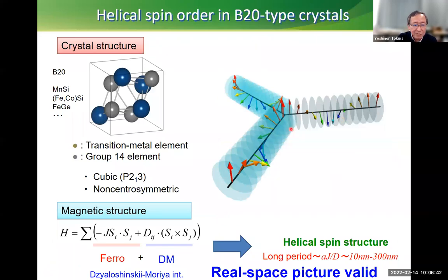So the skyrmion was first identified in the B20-type compound. B20-type compound means a chiral lattice structure, defined as a left-handed or right-handed crystal structure, with space group P213. So it's basically non-centrosymmetric. Originally these compounds tend to show ferromagnetic interaction, but also, due to the lack of inversion symmetry, they show the so-called relativistic spin canting interaction. It's called the Dzyaloshinskii-Moriya interaction, S cross S, namely the orthogonal tendency of neighboring spins.